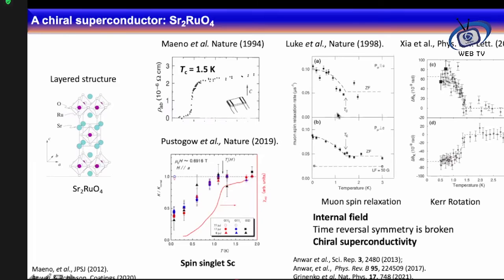But then there was the observation of the internal magnetic field in this superconductor below the superconducting transition temperature. So that means that in the superconducting state, this superconductor has magnetism, meaning there is a magnetic field inside. So this magnetic field means that this is not a normal superconductor. It is an unconventional superconductor that has the internal magnetic field, meaning the time reverse symmetry is broken, as it is broken in ferromagnets.